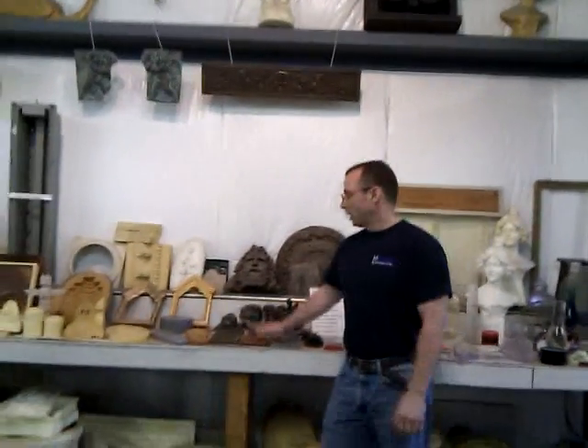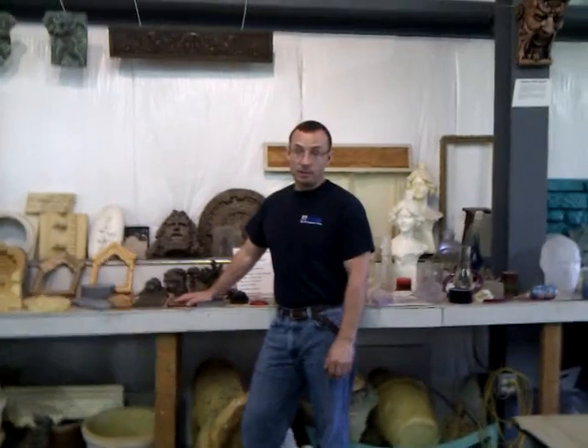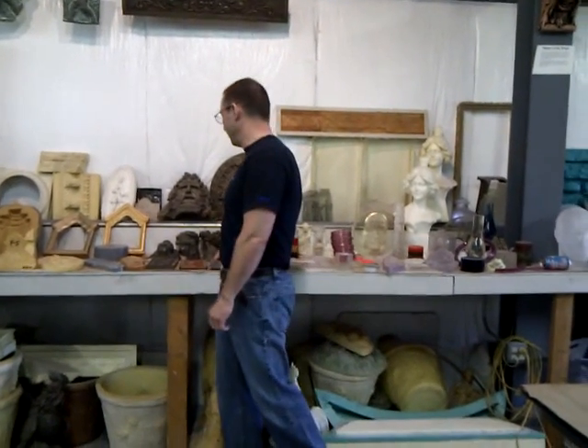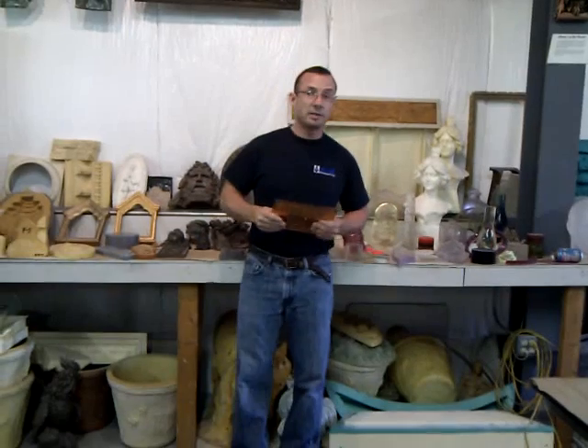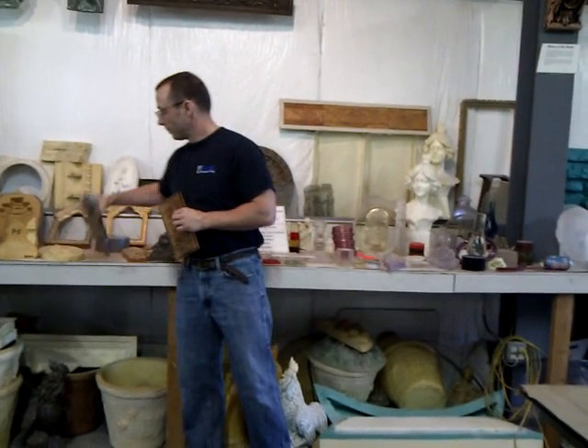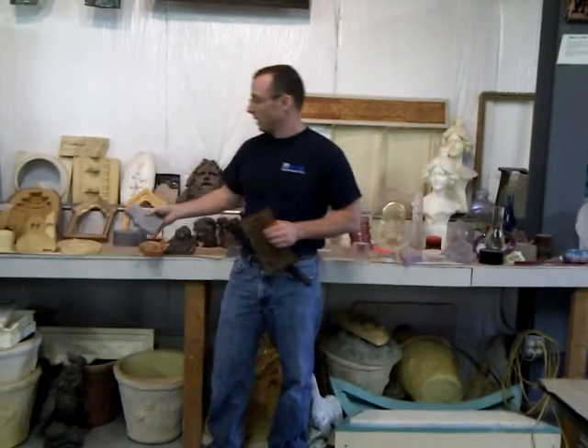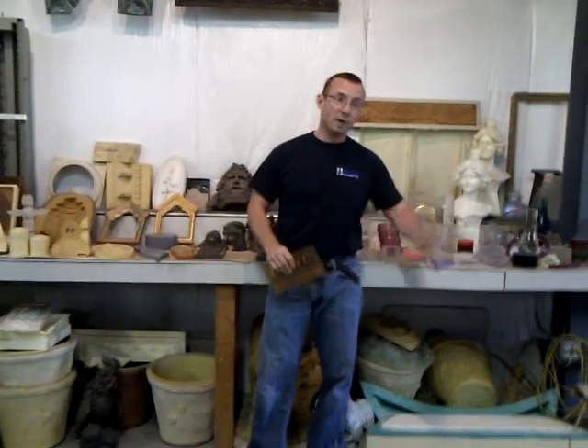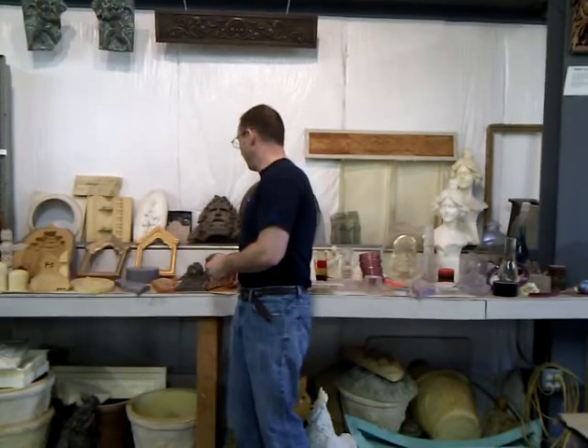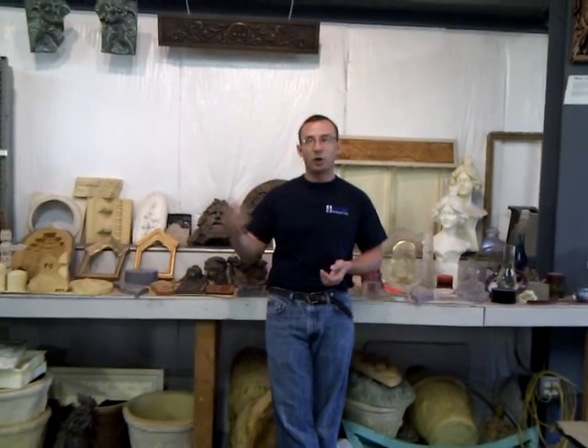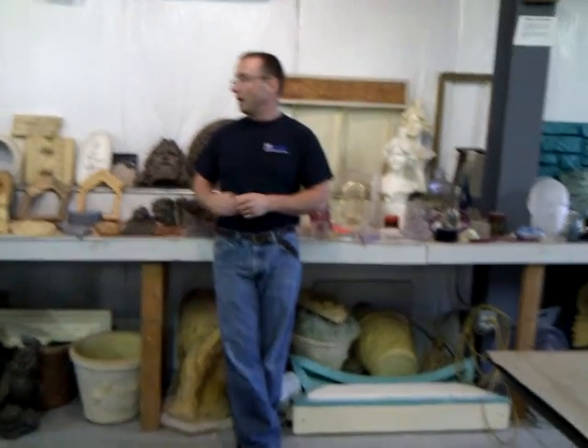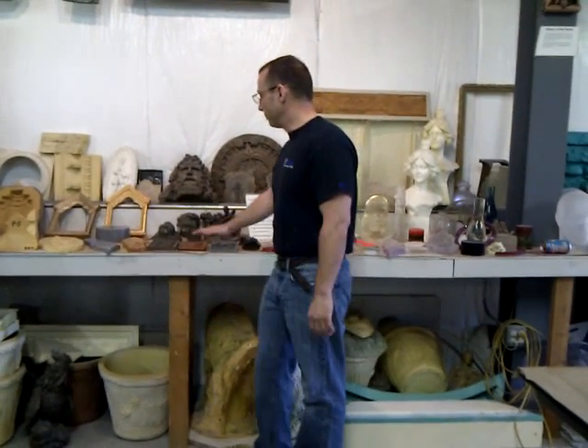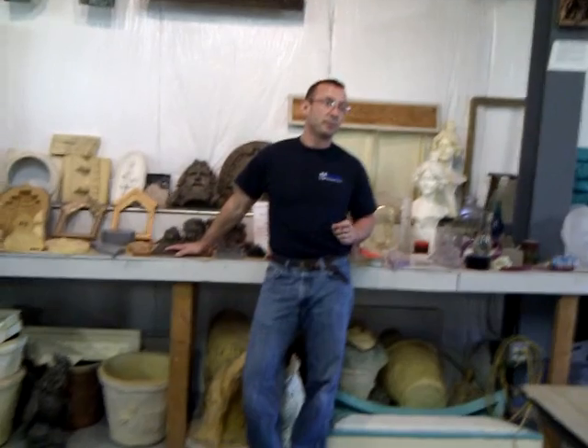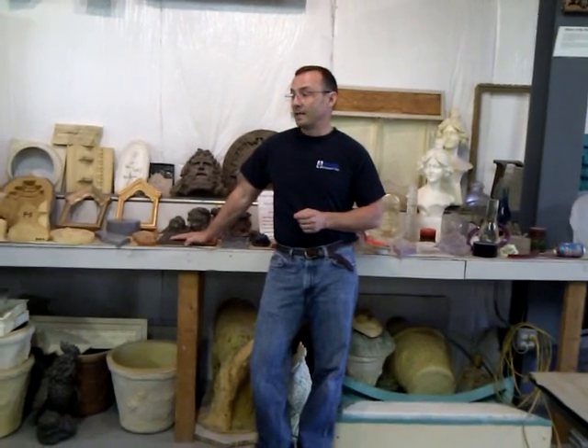We manufacture a line of epoxy casting resins. We have a clear, unfilled epoxy base called 1010, and we have an aluminum-filled epoxy base called 1030. We have 3 different curatives. We have 1212, 1220, 1230, and different combinations of resin and cure will produce different properties in the plastic, allowing you to cast thicker or thinner, give you more or less heat resistance. So the epoxies are the most expensive type of resin that's out there now.